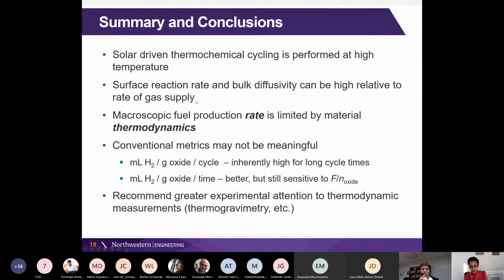It isn't always the case, because you can have a microstructure that doesn't have very high surface area, or you could create very long diffusion lengths, or you might be flowing your gas at a slow rate, so you could be outside of this range of thermodynamic control. But in general, thermodynamic control is encountered quite frequently. So that means that the fuel production rate is limited by the material thermodynamics. So we need better thermodynamics, or at least to select the thermodynamics that gives us good hydrogen production at the low temperature and good oxygen release at the high temperature. So somewhere between ceria and these perovskites, we need to tune that enthalpy to where it needs to be.